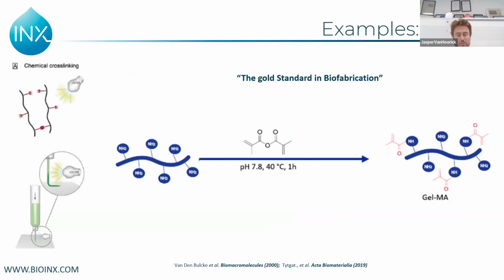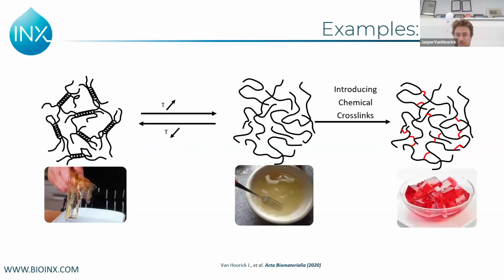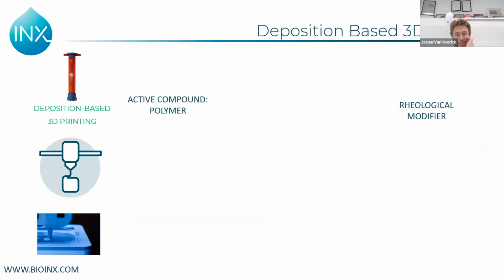So if we think about chemical crosslinking, I already mentioned introducing methacrylates to gelatin is, for example, one of the most popular materials there, which makes the material photocross-linkable. And I already discussed this, so I won't go back into it. But if we look at it from a material point of view, you have your active compound, which is a polymer, and a rheological modifier. In this case, you change your active compound into a photopolymer. And of course, if you have a photopolymer, you need to be able to cross-link it, for which you need a photoinitiator, which is a molecule which induces cross-linking upon radiation.